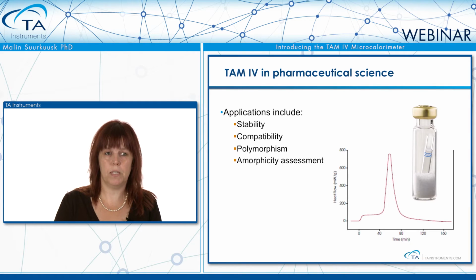An amorphicity assessment is the example shown in this slide, where an amorphous lactose is put into an ampule, where also a small micro-hygrostat is put in with a saturated salt solution that will give a certain relative humidity over the sample. The amorphous part of the lactose will absorb the humidity, and we can see that in the plot. Up to 40 minutes in the plot, we can see the heat of absorption of humidity to the amorphous regions of the lactose. Once enough humidity is absorbed, we induce crystallizations of these amorphous parts, and we see that in a highly sharp crystallization peak in the plot.